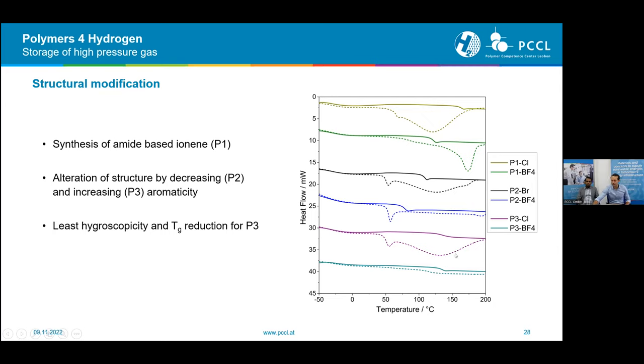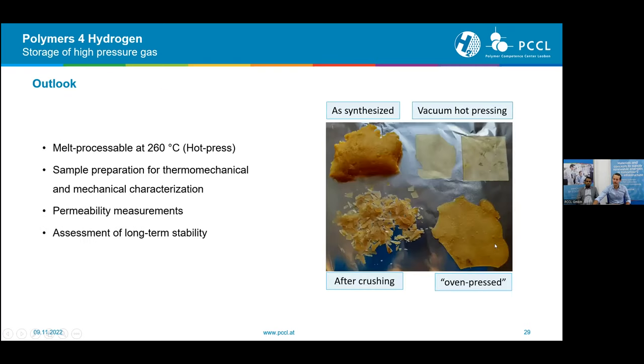So we then chose this polymer 3 with the tetrafluoroborate anion for the further characterization. Of course, for this characterization, we first need to prepare samples. So we tested some different parameters, and we're using a hot press for that. So that's basically just two hot plates on both sides that apply pressure, and then we press the polymer into a certain form. Because we cannot use classical injection molding or something like that, since the polymer is synthesized in our labs. It's a bit limited in material quantity.